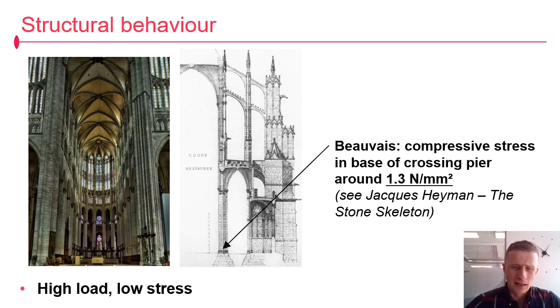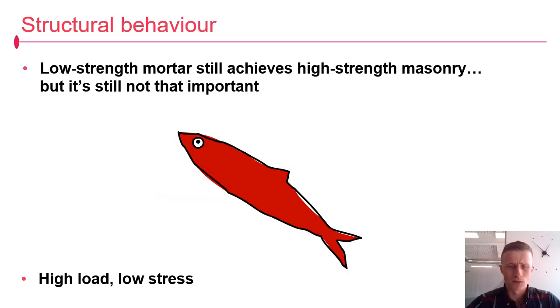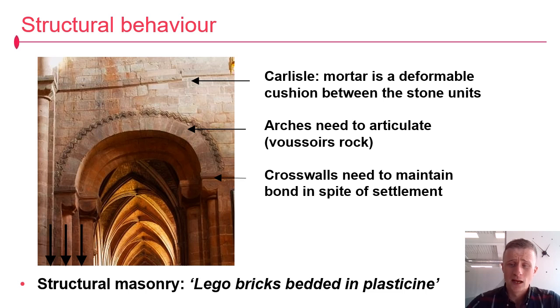Okay, now, but is that high strength actually required? Well, Gothic cathedrals are about as far as you can push load-bearing masonry as a structural material, and still, even in the highly loaded members like crossing piers, you're talking mean compressive stress very low, of the order of round about 1-2 Newton per square millimetre. So high load, low stress, thanks to the massive section area. Now, so you can get high strength masonry out of low strength mortar, but as we've seen, high load, low stress, thanks to the massive section area, strength still isn't that important. So it was a bit of a red herring to make the point. Okay, what is important about the structural behaviour of the mortar joints is its deformability. So that's the deformation modulus.